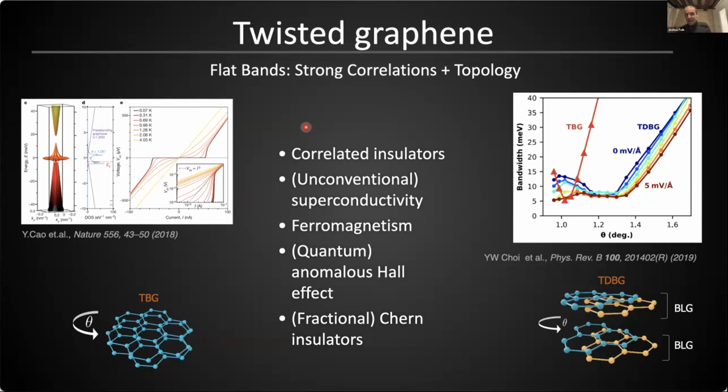And whether they're exactly as flat as in monolayer, I think probably not. So people say that the bandwidth in monolayer is something like 5 meV. In double bilayer, it's maybe, well, according to this graph, 7. It's somewhat worse, but not categorically worse. And you have this added tunability. So that was one thing that got us very excited about it in the beginning.